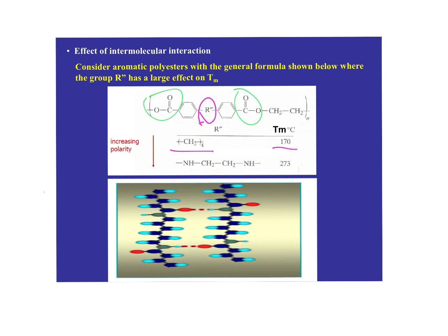But if we swap out some of that for polyamide type structure, now we're adding back in nitrogen, which is capable of hydrogen bonding with its neighbors, all right? And our melting point jumps back up to 273 as a result of that. All right, so we can engineer those melting points, also knowing that it's engineering the mechanical properties at room temperature.